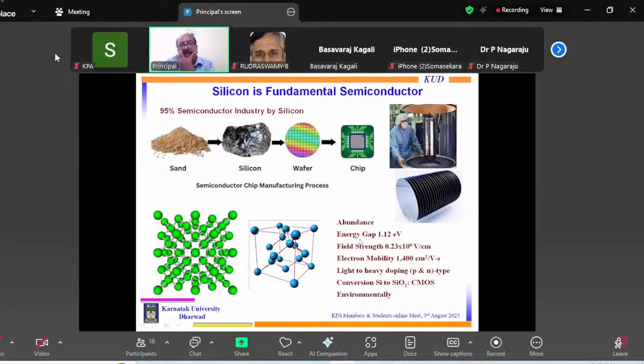And if I look at the general properties of silicon, it is quite abundant because sand, the raw material, is very abundant. The energy gap of silicon is 1.12 electron volt, very suitable with respect to the solar spectrum and for many other applications. Another parameter of any semiconductor is field strength. What is the maximum electric field a material can carry? That is almost 1,000,000 volts per centimeter, very reasonably high. Electron mobility is quite good, 1,400 centimeters squared per volt second.